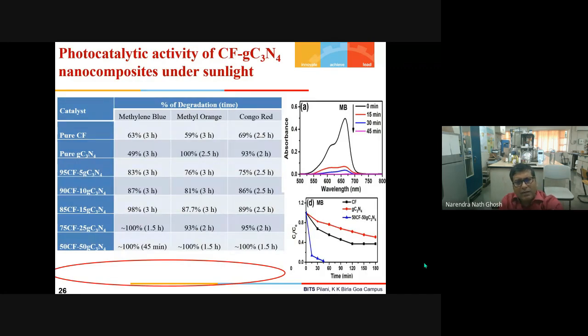So this table shows that first, as I said, we have taken different model dyes like methylene blue, methyl orange, Congo red, and we have performed the reactions, I'm sorry, on the title, it is under solar light simulator, not sunlight. In our lab, we have a solar light simulator, as it gives the same constant illumination and intensity, instead of depending on natural sunlight, which may vary at different times of the day and different days. That's why we are using the solar light simulator. So we have performed these photocatalysis reactions using pure cobalt ferrite, pure graphitic carbon nitride, and several compositions of the catalyst.